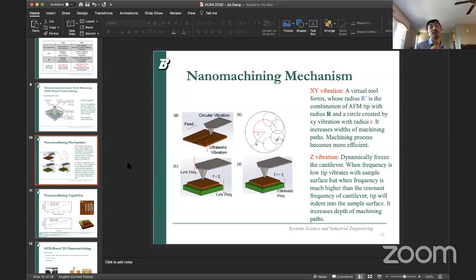And in terms of Z vibration, the frequency in the Z direction is very important for the cantilever. The mechanism here is that we use a very high ultrasonic vibration frequency, about the 2 megahertz range, which is much higher than the cantilever frequency, because the resonant frequency of the cantilever is about 160 kilohertz. So we have to use a much higher vibration frequency in the Z direction to make the tip indent into the surface. In that way we can make 3D structures. Otherwise, it's only 2D and cannot change much.